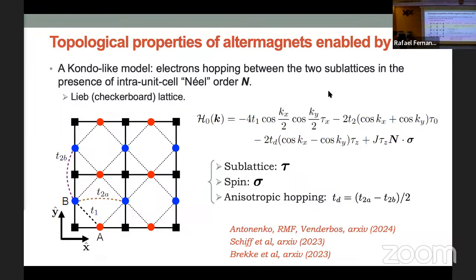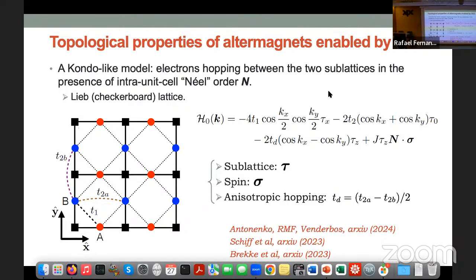The Lieb lattice is a 2D lattice that has, as I'm showing here, two different sublattices. So it has two atoms per unit cell, which are here blue and red. But they have these black squares here. They are the non-magnetic atoms in this model. If you think of a copper oxide layer, that's exactly what it is, right? The oxygens are this, and the coppers are here. Now I can have spin up and spin down, but you see I also have two sublattices that I call A and B.